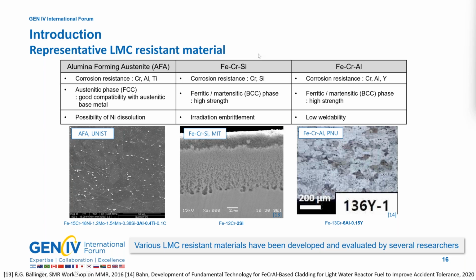The iron chrome silicon system includes chrome and silicon as corrosion-resistant elements and has a BCC structure with high strength, but there is a concern about irradiation embrittlement. The iron chrome aluminum system includes chrome and aluminum as corrosion-resistant elements, has a BCC structure with good corrosion resistance, but its weldability needs to be verified.